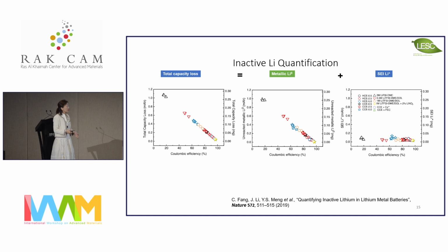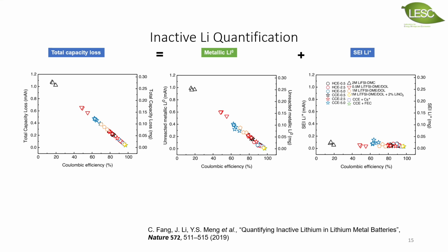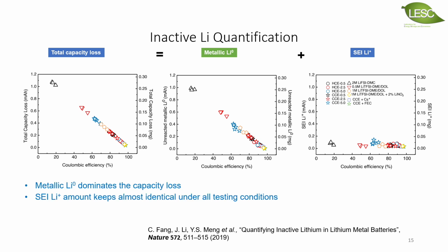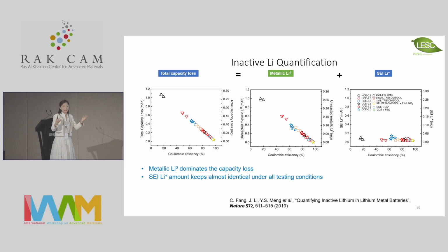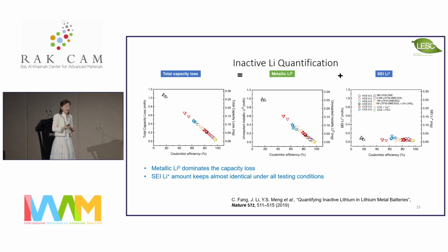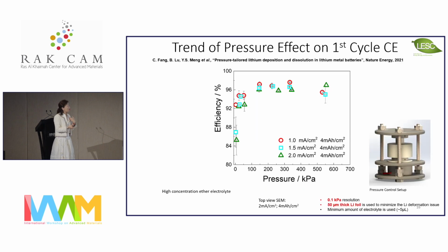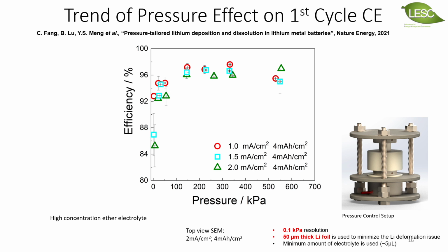So in this work, we showcase that in all the electrolytes we have investigated, all the efficiencies perfectly correlate with the amount of unreacted lithium, and it's not caused by the so-called SEI layer. And this finding, maybe to external people, is not that meaningful because, so what? If you have a lot of dead lithium isolated by the SEI, your battery cannot cycle 1,000 cycles. But for people in the battery field, I think we were able to translate the knowledge into a very effective engineering mitigation method. So because lithium is very soft, if we have a lot of dead lithium that's isolated, let's try something mechanical, all right?